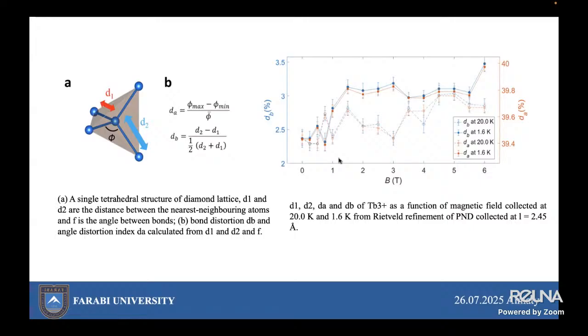In this picture, you see the distances as a function of magnetic field collected at 20 Kelvin and 1.6 Kelvin, given for different temperatures, from the Rietveld refinement of the patterns, with a wavelength of 2.45 angstrom.